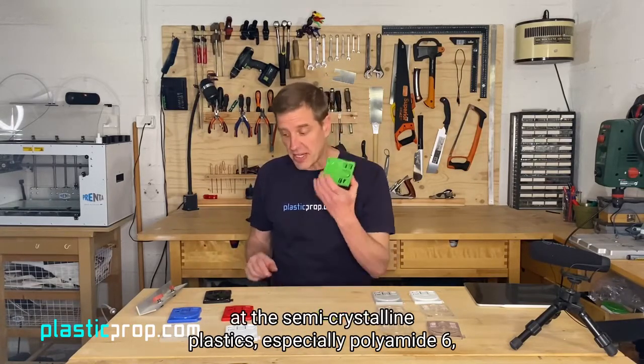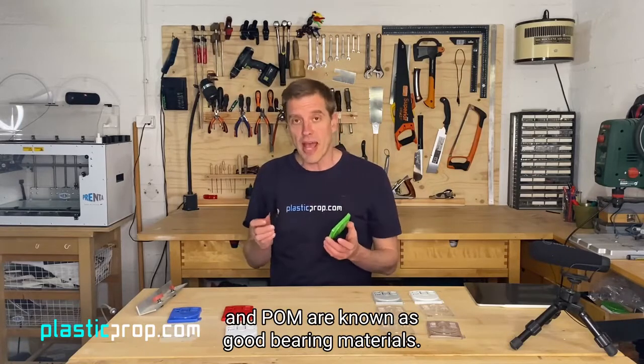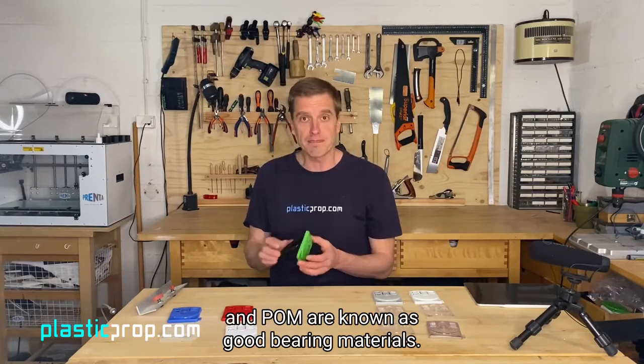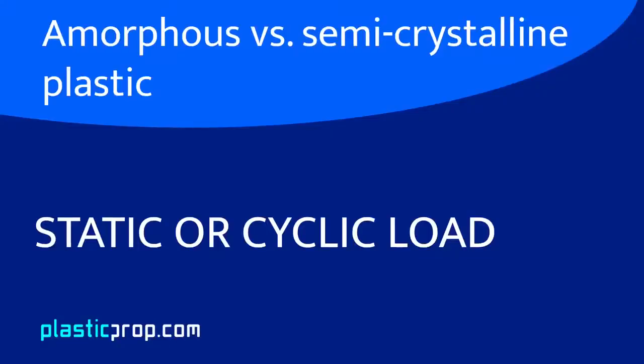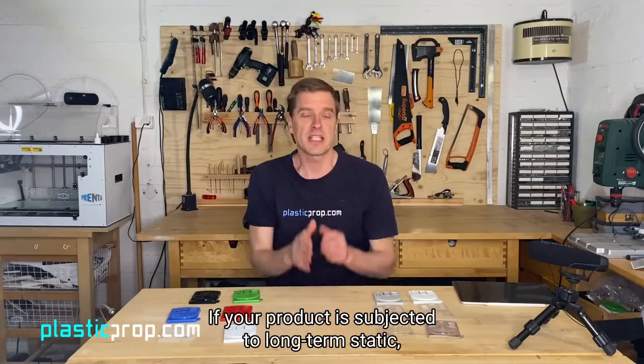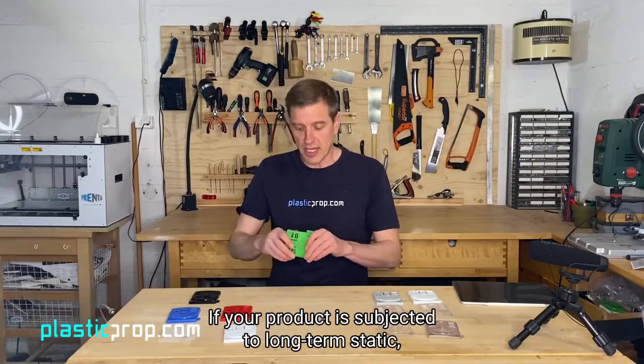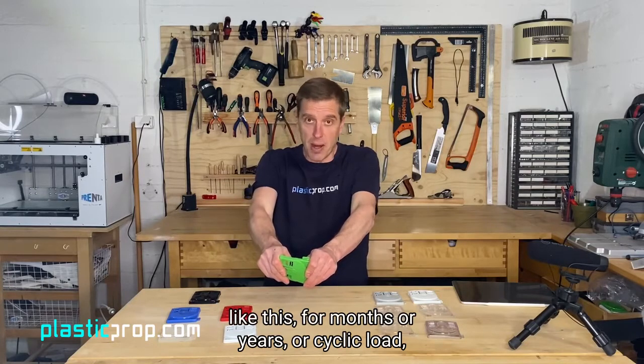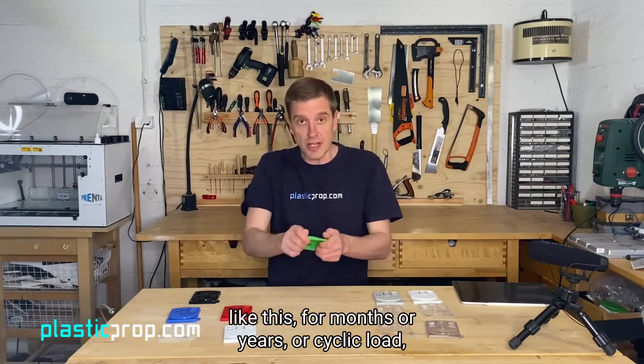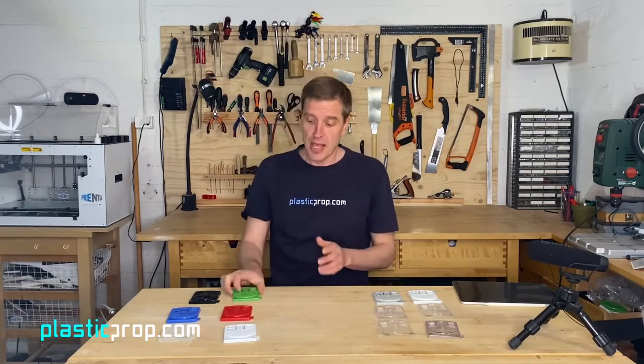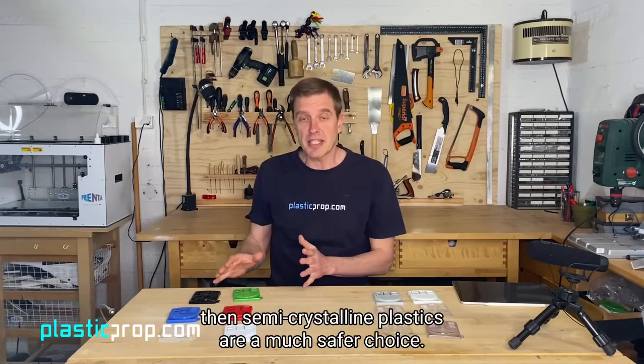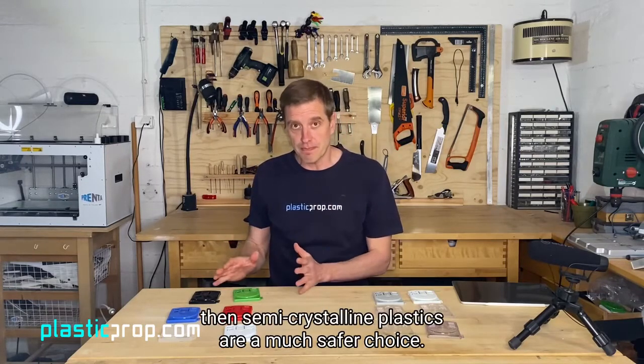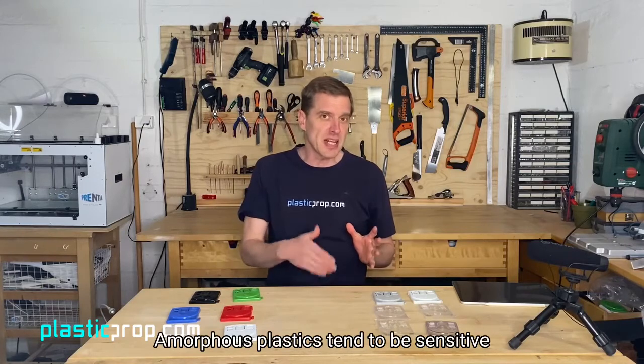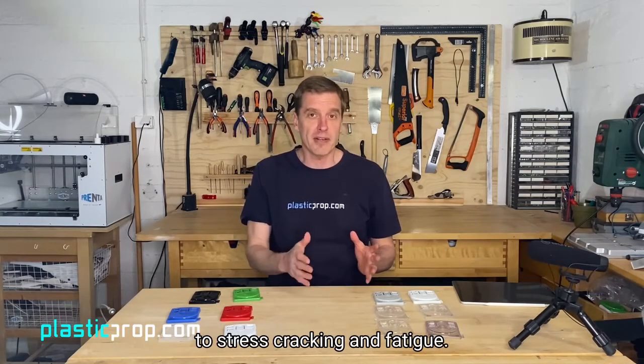Especially polyamide 6 and POM are known as good bearing materials. If your product is subjected to long-term static load, like this for months or years, or cyclic load, then semi-crystalline plastics are a much safer choice. Amorphous plastics tend to be sensitive to stress cracking and fatigue.